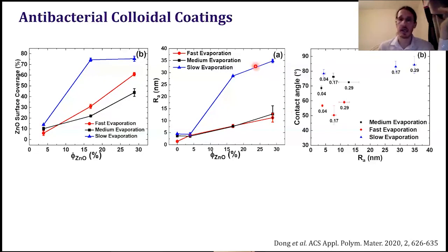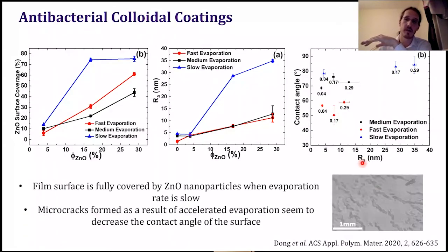And one thing we notice is that the contact angle of these really slow evaporated coatings is much larger. But I think in this case, it is probably because when we are evaporating slow, we have higher roughness, so we have higher contact angle. And then we have really low contact angle when we evaporate really fast. But this is also because when you evaporate really fast, you can see here in an optical image, there are some cracks developing in the film. So that's probably what is lowering this water contact angle.